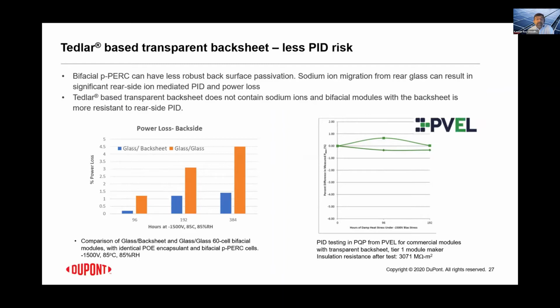comparisons of a glass transparent Tedlar backsheet, which is shown in blue bars, versus a glass module of exactly similar build with a similar BOM, but just the backsheet being replaced by a glass. And we are showing the power loss over here on the rear side of a bifacial p-PERC module with PoE encapsulant over here. And we are seeing a much lower loss of power on the rear side. We believe that this has to do with the lower amount of both shunting type as well as polarization type of PID that's happening in these modules. This work is still ongoing.